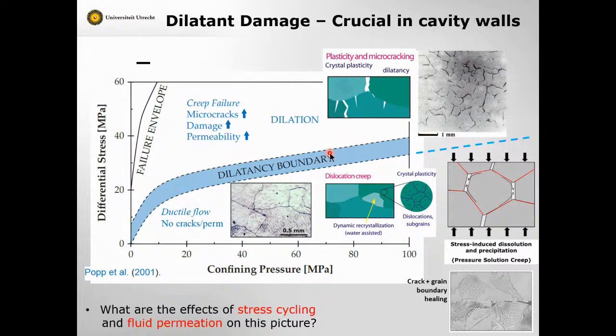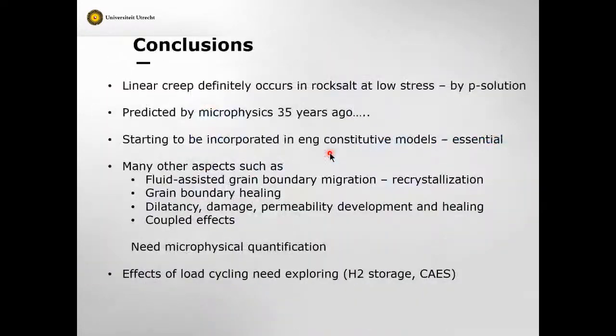So again, microphysics is needed to constrain extrapolation of what we measure in the lab to longer term, or let's say multi-cyclic behavior for a hydrogen storage cavern, something like that. Where was I? Okay, so I've reached my conclusions. Linear creep definitely occurs in rock salt. This linear viscous creep by pressure solution definitely occurs in rock salt at low stress. That is now clearly demonstrated.